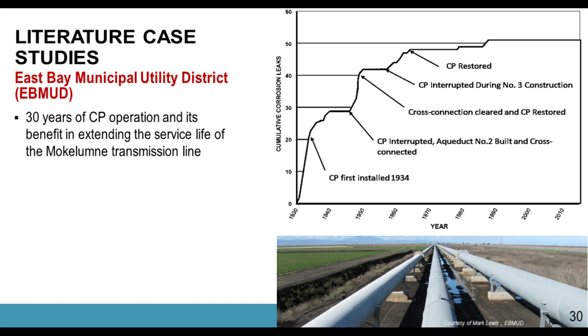However, as you see, after application of even the first type of CPs, you see a reduction in breaks and a stabilization in overall breaks. And then every time they interrupted their system to build a new addition or new cross connection, they had an increasing number of breaks and a slowdown after they restored their CP system. So this is a great evidence for 30 years of successful application of CP on their system and extension of the life for this aqueduct.